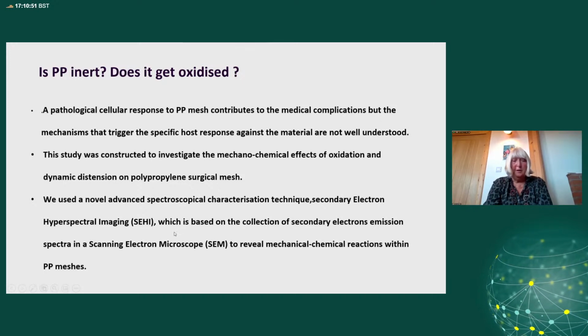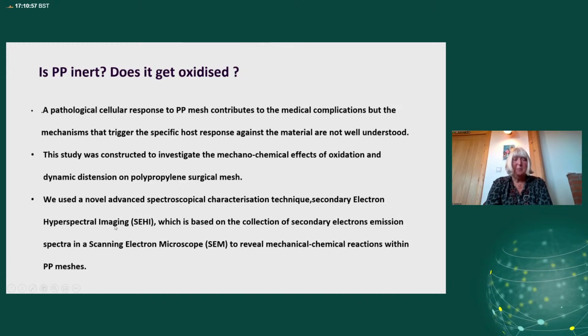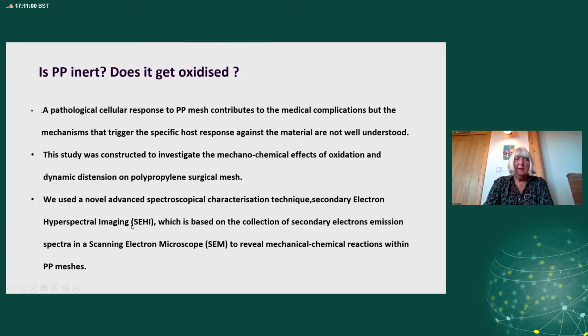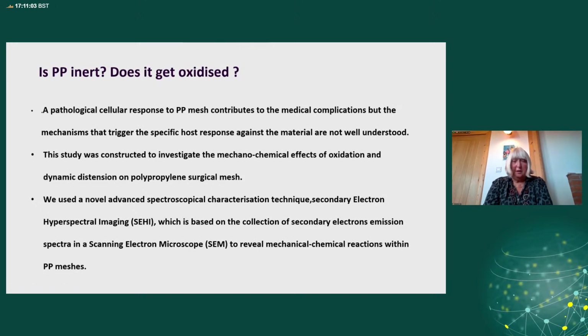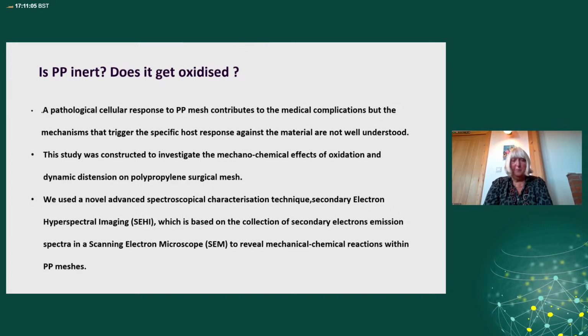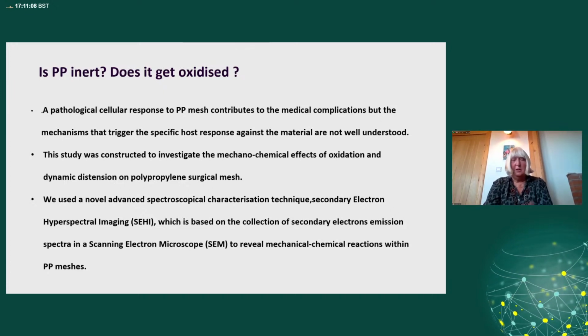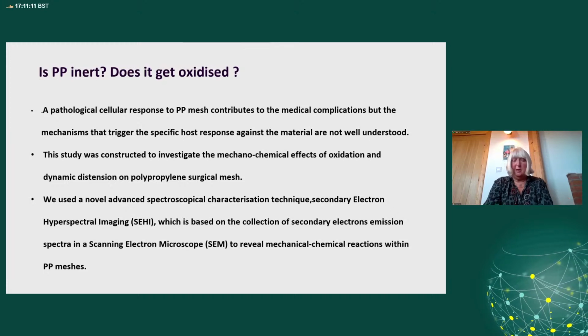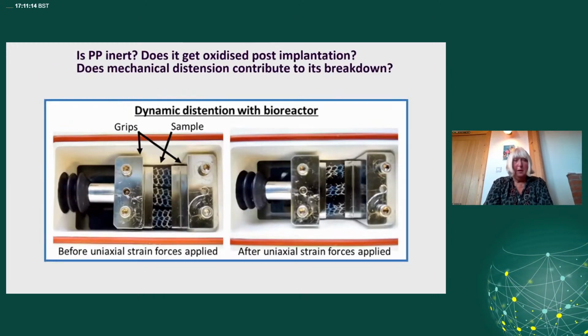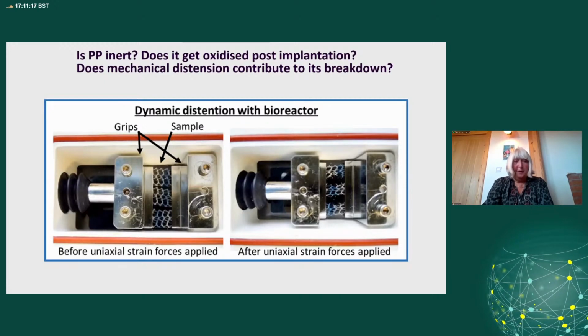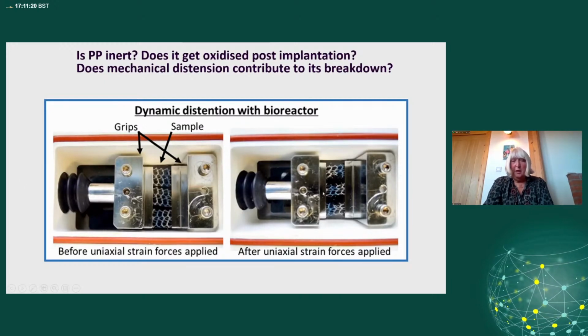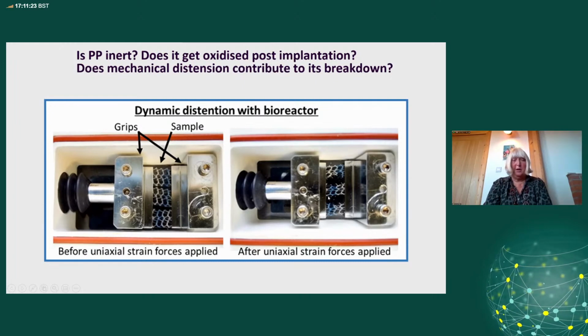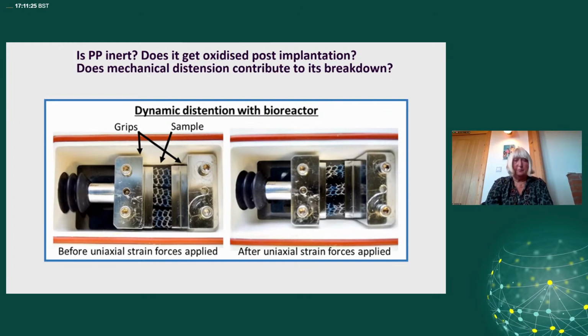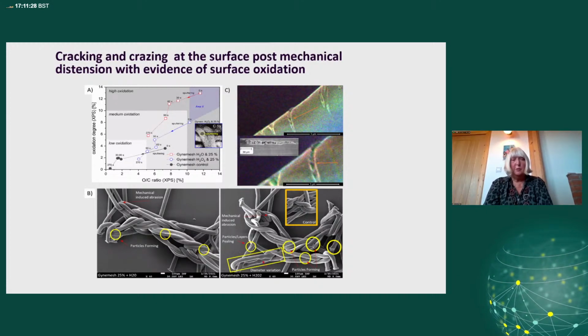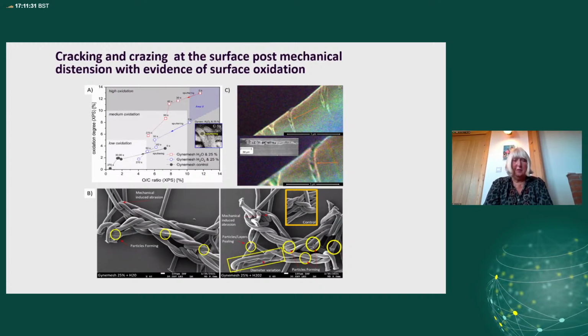And then we used this novel advanced spectroscopical characterization technique, secondary electron hyperspectral imaging. Basically, you look right down at the fingerprint of the bonds in the polymer to ask whether they're oxidized or not. And you also do this on a 2D landscape using electron microscopy. So the simple bit first, we clamp the fibers in this bioreactor and we spend 3 days just giving them a gentle workup. So that's our mechanical distension. The oxidative stress is exposure to hydrogen peroxide, I think 16 hours.